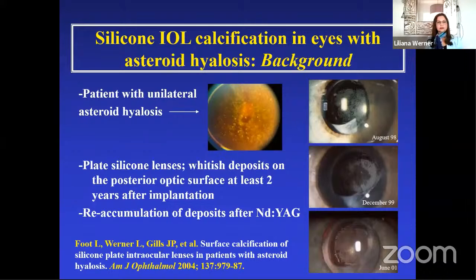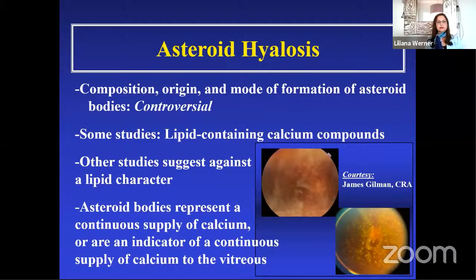We first described this problem in association with single-piece plate-type silicone lenses. The calcified deposits occur only on the posterior surface of the lens, and they can be at least partially removed with a YAG laser. However, there is usually a reaccumulation of deposits after this procedure. Different studies demonstrated that the main composition of asteroid bodies is calcium and phosphate. Therefore, they represent a continuous supply of calcium, or are an indicator of a continuous supply of calcium, to the vitreous.